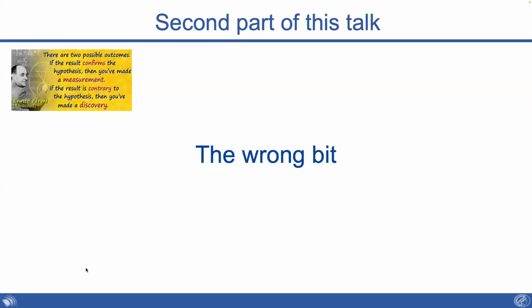Remember, this is something that Demler explained to me and made me feel very ignorant. In BCS, the problem is not the amplitude of the phonon, it's the noise of the phonon. If you now drive a classical phonon coordinate to large amplitudes, that does not tell you about the important term that you have in BCS. When the second guy jumps on the mattress, you're not interested in how far the mattress goes down, but how elastic it is. What you're interested in is how much the mattress is fluctuating.